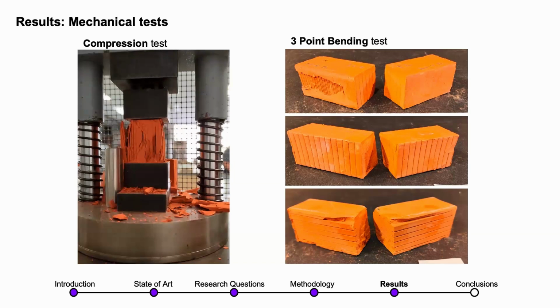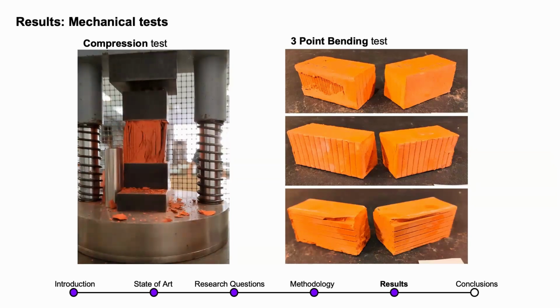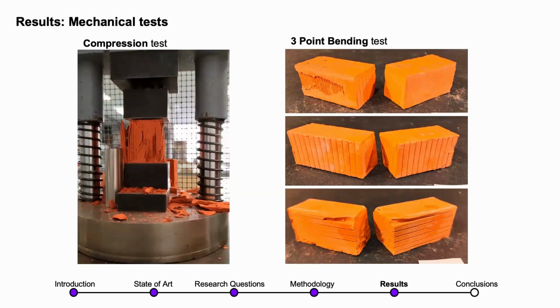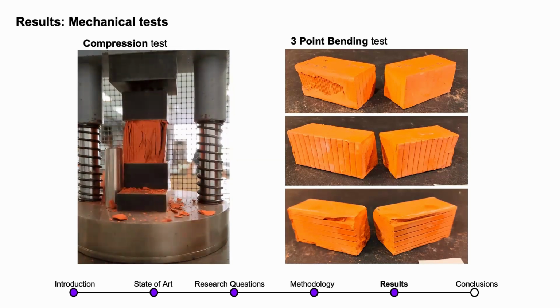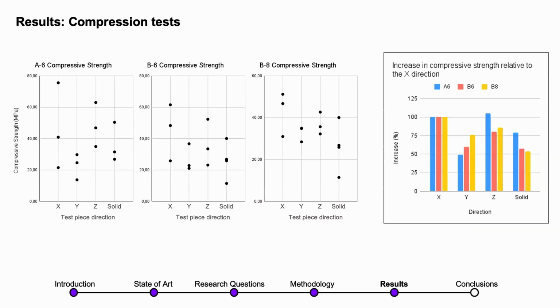We can see in the mechanical tests that the discontinuities caused by the 3D printing process create weak planes for the material to break through. These are the horizontal joints between the printing layers and the vertical joints between the printing lines. And we can see a more irregular break here because we have a continuous material. Regarding the results of the compressive strength, we see a very big dispersion of the results for the X, Y, and Z directions. These are the 3 batches that we manufactured, but we can see a clearly differentiated behavior of the material. If we take the X direction as 100% compressive strength, we can see this behavior for X, Y, and Z.